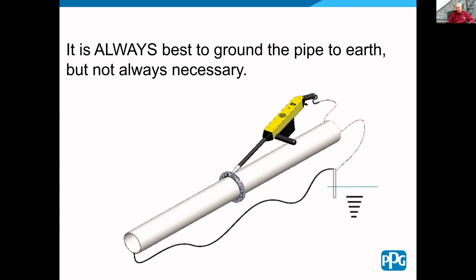It doesn't work as well on concrete. It doesn't have the surface area that the wire and sandbags do. So if you cannot get a good direct ground to the inside of the concrete with a moisture level high enough to pull current, then this capacitance ground wire, sandbag, and ground wire from the unit is just fine.